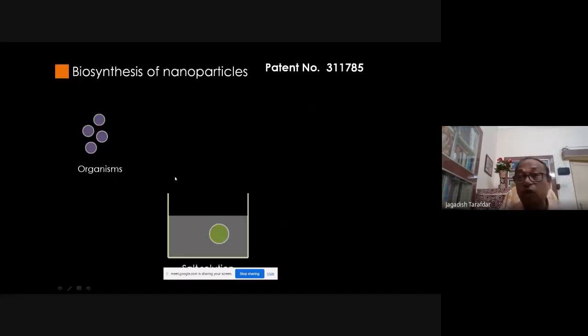But in all these methods, the physical, chemical, and aerosol methods, the particles are naked. So unless you coat them, they immediately agglomerate and become nanoscale particles or microparticles. Probably you know the difference between nanoparticle and nanoscale particle. Nanoparticle: the size is less than 100 nanometer. Nanoscale particle: the size is 100 to 1000 nanometer. The nanoscale particle is good for engineering and medicinal purposes. They don't bother about nanoparticle.